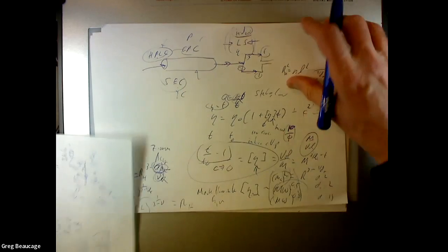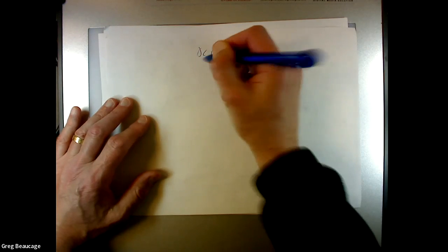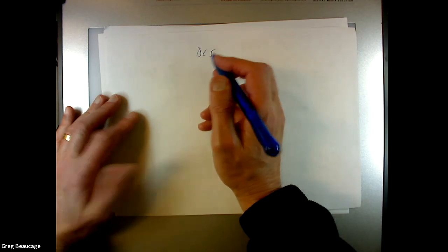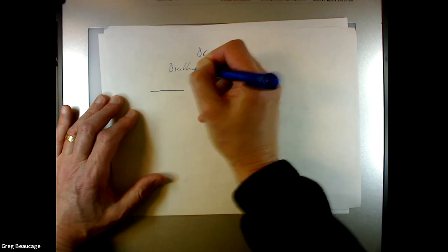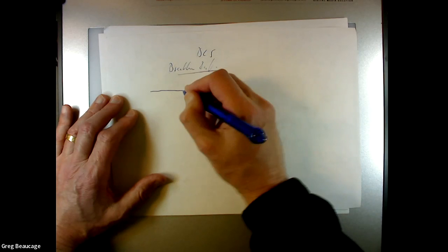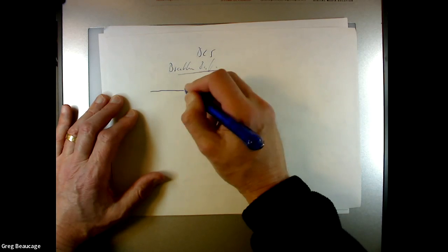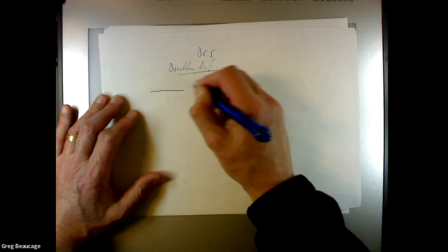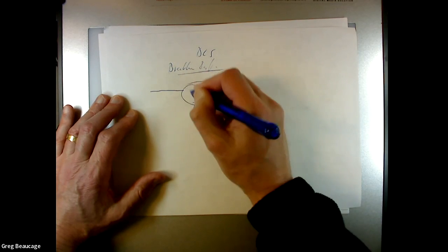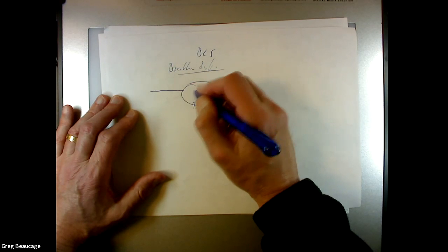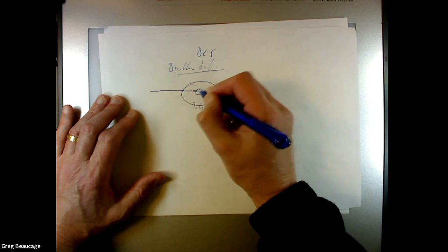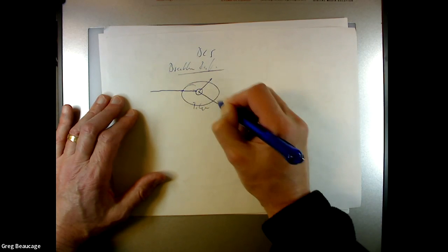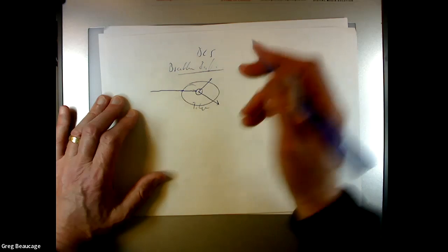So that's one way. The other way to get it is to do dynamic light scattering, which is sometimes the same machine that you're doing light scattering with. Brookhaven Instruments makes a machine for this. So you have a laser. It's not a high power laser. It's like a helium neon laser, and there's a big bath of toluene. And then in the middle you have a cylindrical sample area. So the beam comes in. The idea is to put the sample in the middle and the beam goes straight through at 90 degrees to the wall, so there's no reflection.